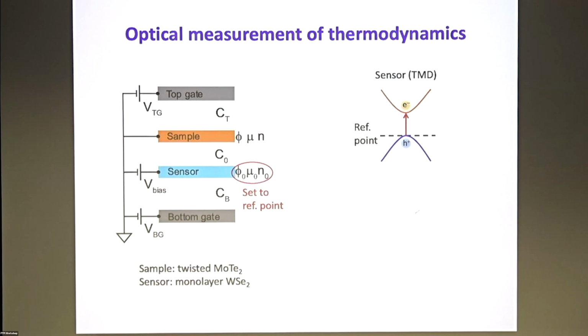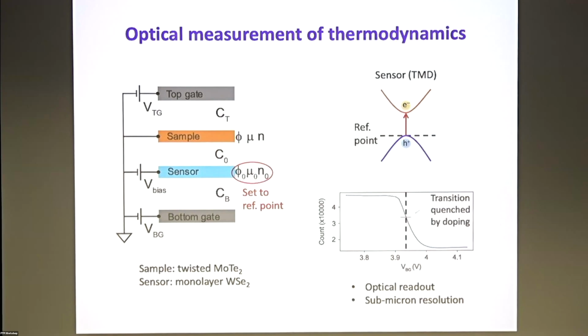And it has a band structure. This is the band structure of the sensor, which is a very trivial semiconductor. Naturally, you would like to pick a reference point such that you fix the Fermi level of this sensor to touch just one of the band edges, either the conduction band edge or the valence band edge. To read that out, you can look at the strength of this vertical transition that promotes an electron from the valence band to the conduction band, leaving a hole behind in the valence band. Once your Fermi energy moves to the valence band maximum, the strength of this transition shows a broadened step function, because once you put the Fermi energy there, you introduce Pauli blocking for the optical transition. As a result, this step function provides a very natural reference point.